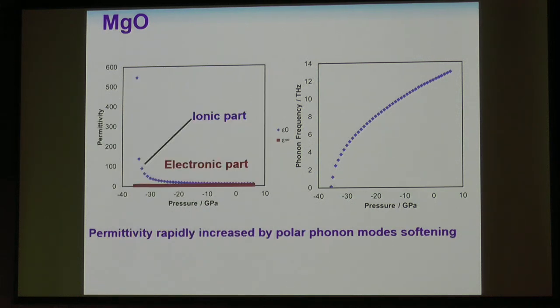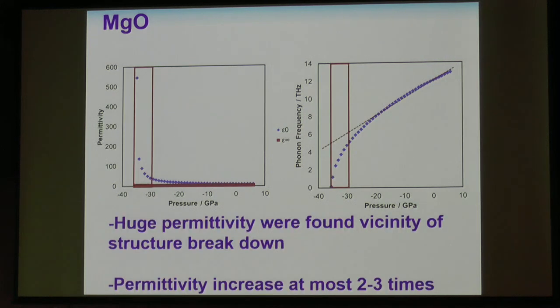At the same time, the dielectric constant, the permittivity, goes up, as shown here. Only the ionic part shows this divergence. The electronic part doesn't change much. So the permittivity rapidly increases with polar phonon mode softening. But this permittivity divergence was found in the very vicinity of structure breakdown. This calculation shows that at this negative pressure the structure is broken. Apart from this area, the permittivity increases at most 2 to 3 times, so not so significant.